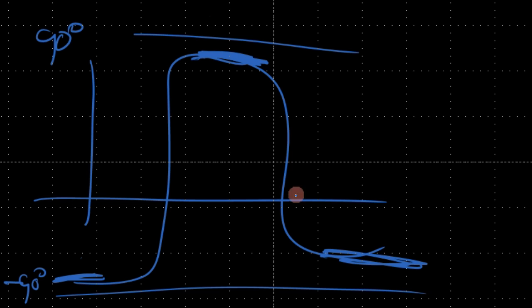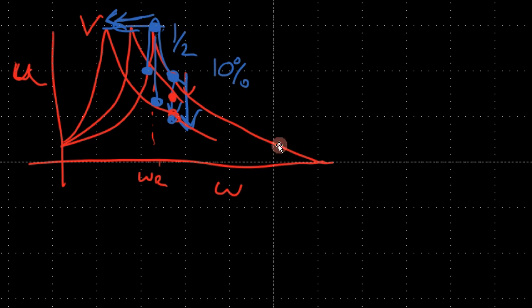It's almost like it gets stuck. Basically, as I showed here, if you increase much past the resonance frequency you're going to get a very small vibration, even smaller than you would get at off-resonance. So you don't want to drive it at a higher frequency, but you may want to do that because you want to, for example, excite megahertz type vibration for a mode which is not ideal. If your application requires a specific frequency but doesn't allow you to design the transducer in a shape that allows for resonance, then you may make things work just by driving off-resonance.